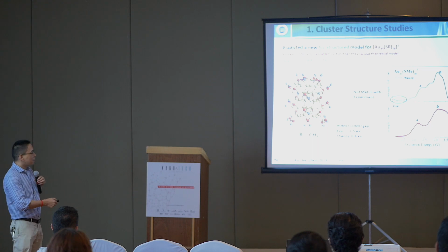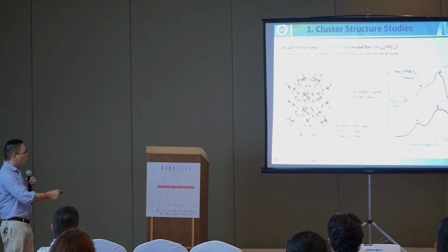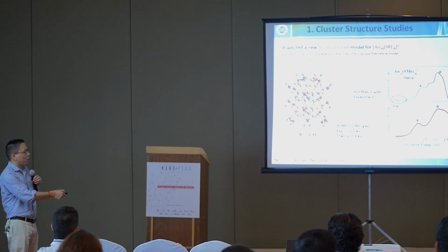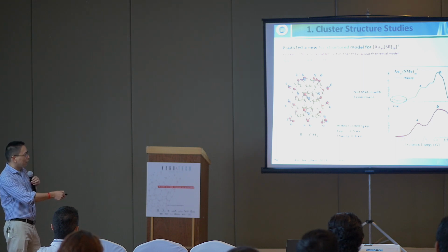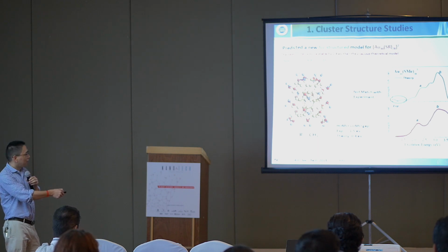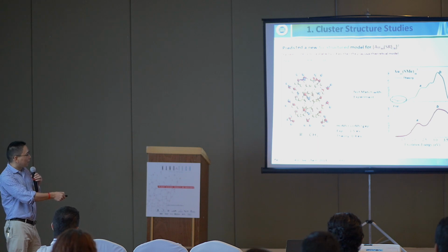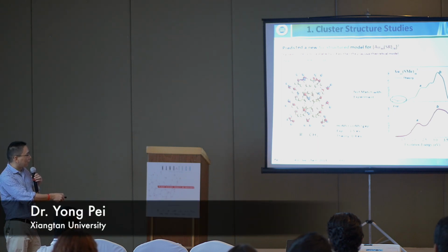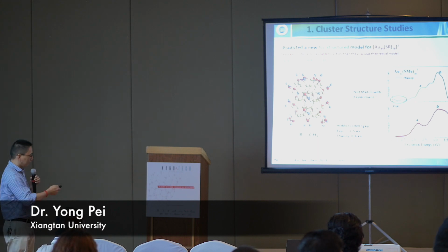But one thing is different from experiment. When we use the dianion state, when we add two electrons to the cluster, the spectrum calculated from TDDFT is much different from the experimental curve. Here is the experimental curve. Here is the TDDFT result. We can see from the experimental curve, the optical gap is about 2.5 eV, but the TDDFT predicted a very small optical gap, only about 0.4 eV.